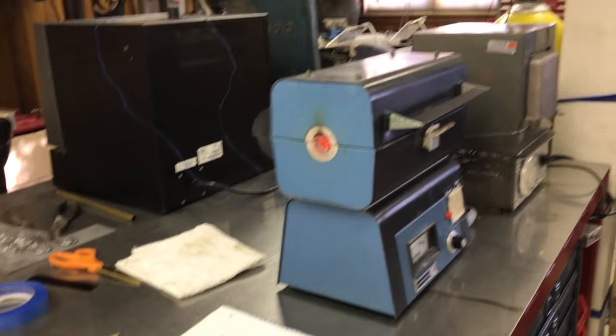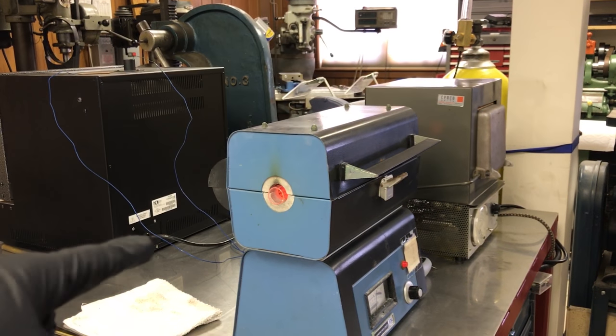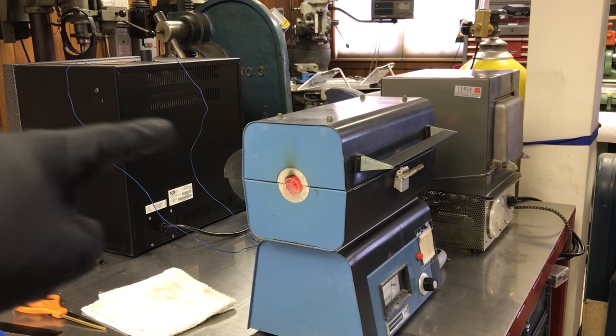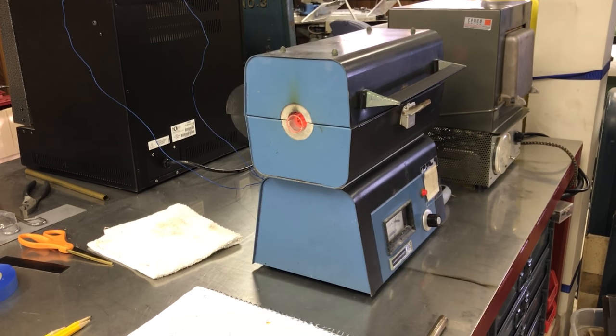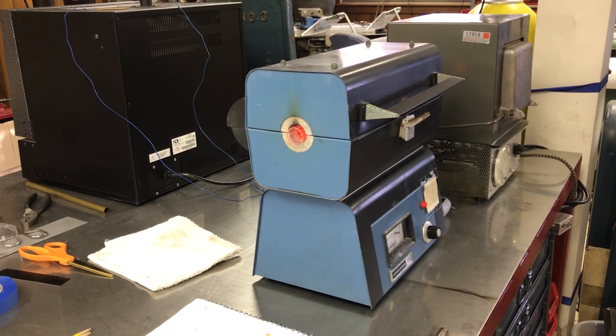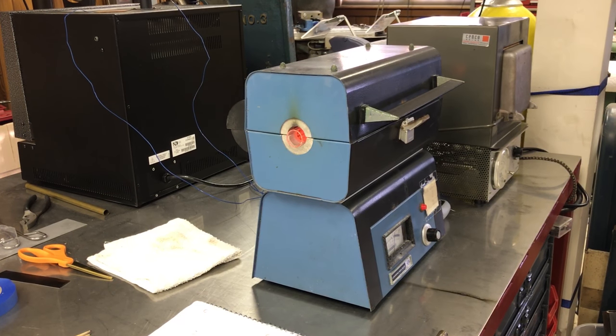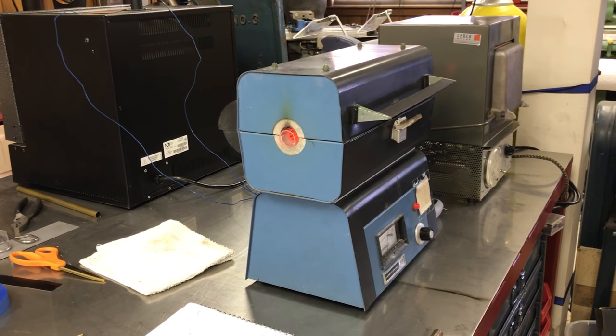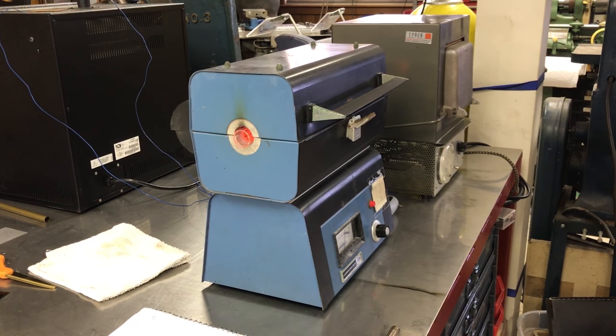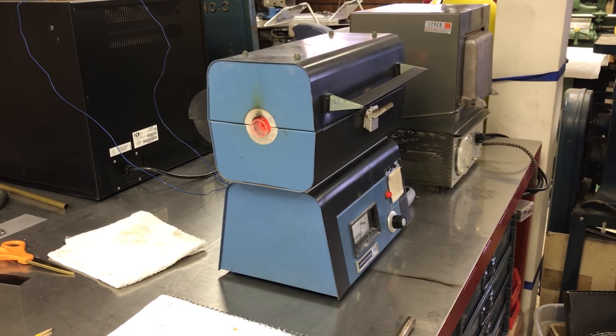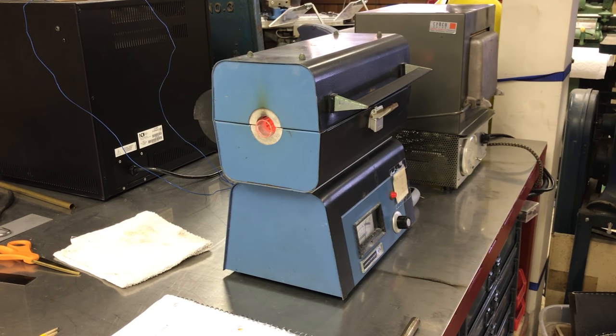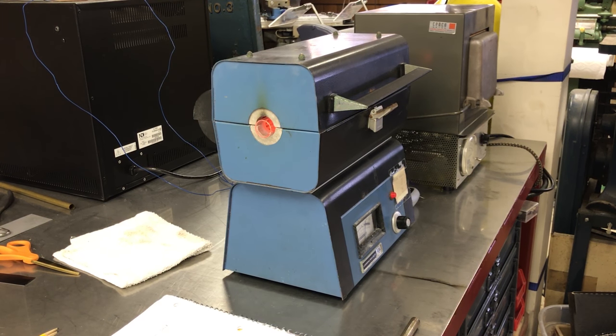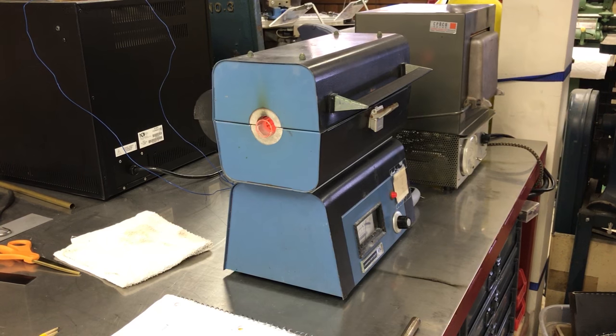I'm also going to take the nozzle from that yellow nitrogen tank and position it so it's blowing a small amount of nitrogen through this furnace and that will allow for a lower resistivity of the silicon wafer once we're done with this and it'll overall give us better electrical characteristics. So that nitrogen is basically replacing the oxygen. So normally we'd have 20% oxygen, 70% nitrogen-ish in there. So we're increasing that nitrogen content quite a lot, which is great. So I'm going to go grab the wafer and we'll go ahead and do that.